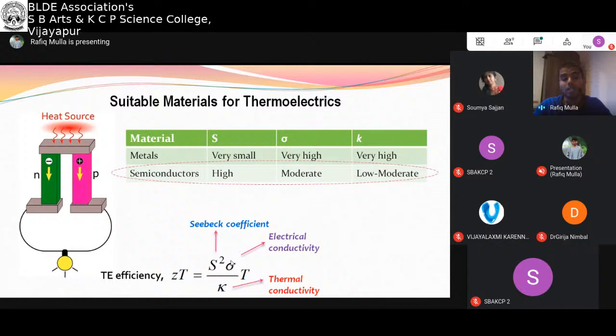So doping or impurity, adding impurity, or making composites. By making composites, you can reduce thermal conductivity. So because of scattering of phonons in the composites, you can significantly reduce K. By doping, you can tune sigma as well as S. Of course, it also affects K, but it is not much. But mainly sigma will be affected by doping. Similarly, by nanostructures, you can significantly improve S as well as you can significantly decrease K, and because of that, you get better value of ZT.